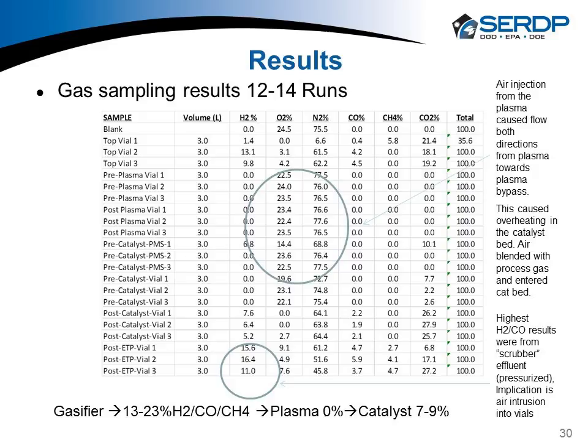Probably the highest percentage of hydrogen and carbon monoxide was after we did that scrubbing step, where we were pumping the gas out of the top of the gasifier, going through the JP8, and then ejecting that gas into the GC mass spec vials. And in this case, we were seeing about 13 to 23% hydrogen, carbon monoxide, and methane.